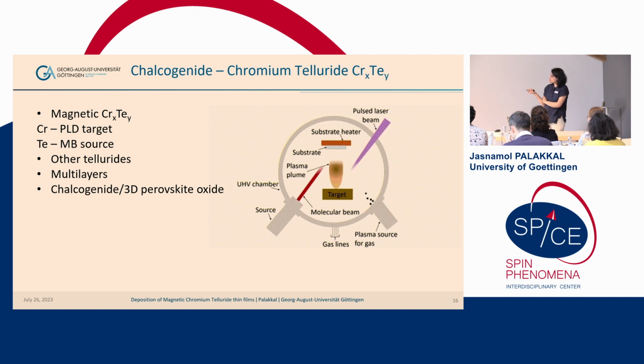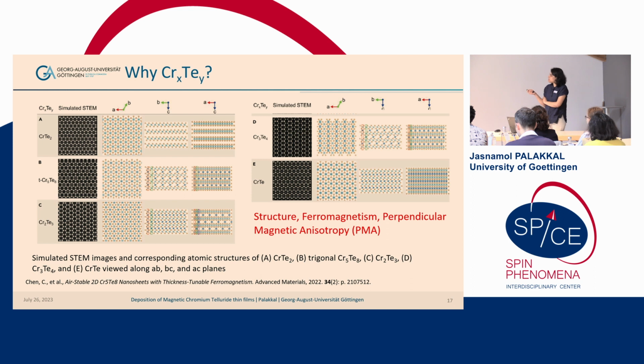Our long-term plan is to grow chalcogenide and 3D perovskite oxide interfacing, because if you want to grow a 3D perovskite oxide, the best technique is to use a PLD, and if you want to grow a telluride, you need a molecular beam source. So we believe that we could easily combine these 2 versatile material systems in our experimental setup.